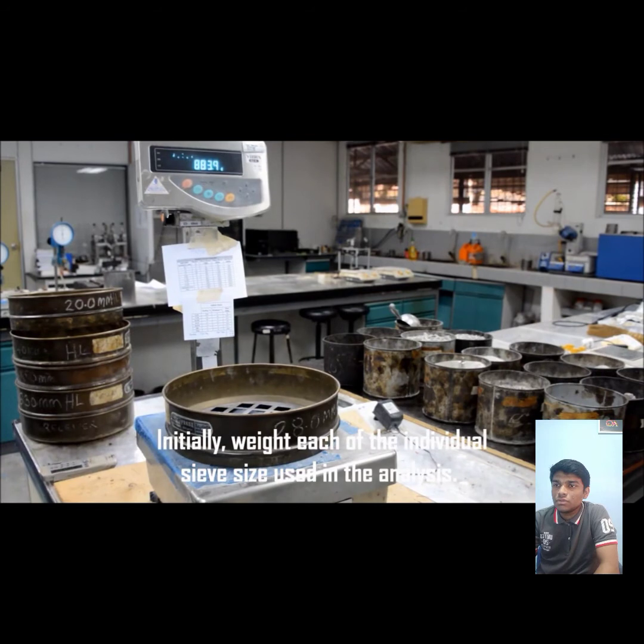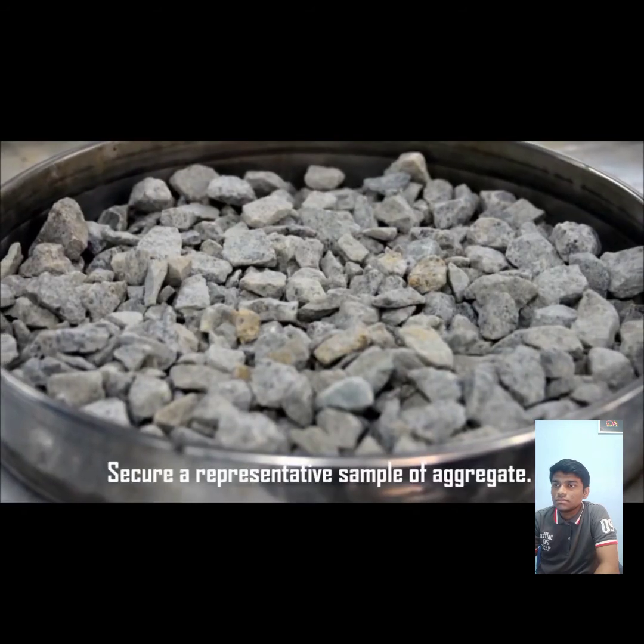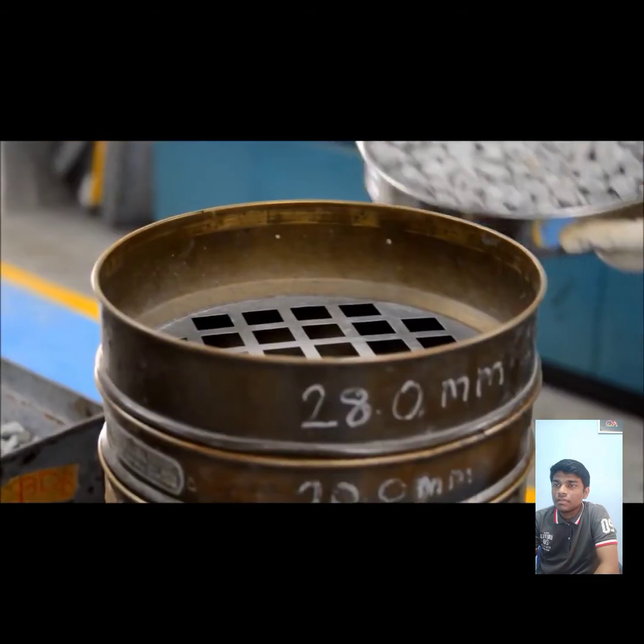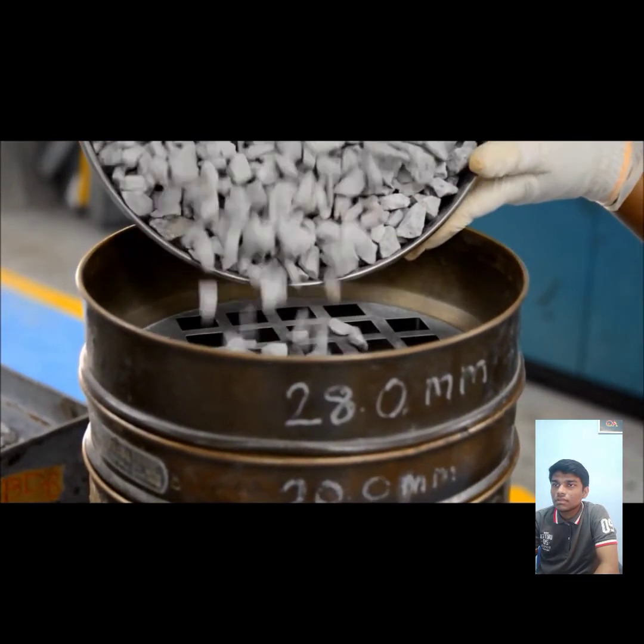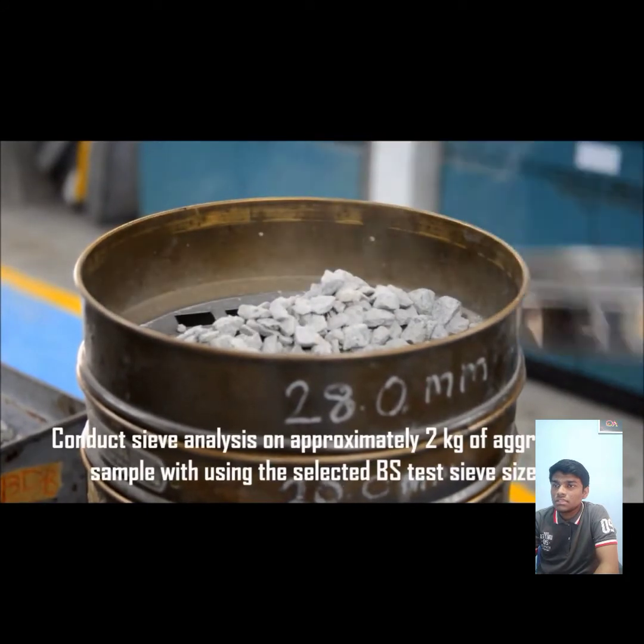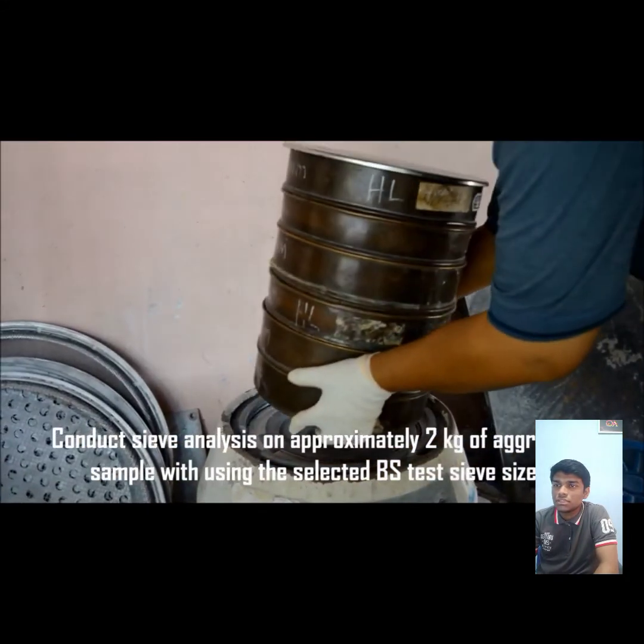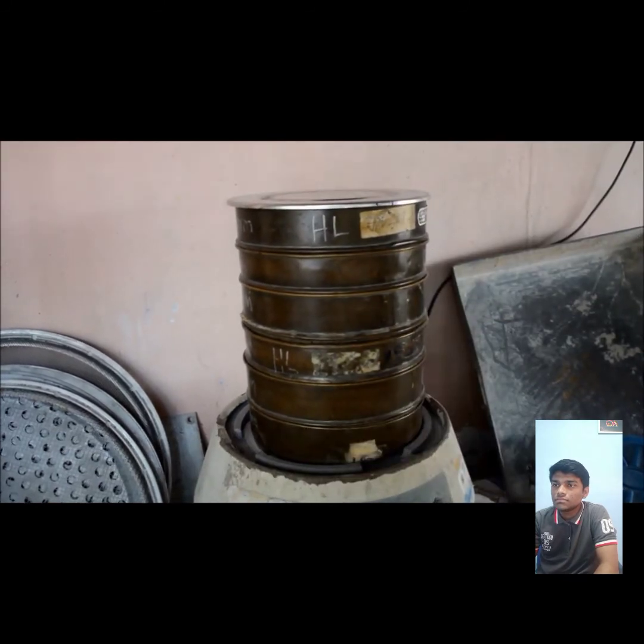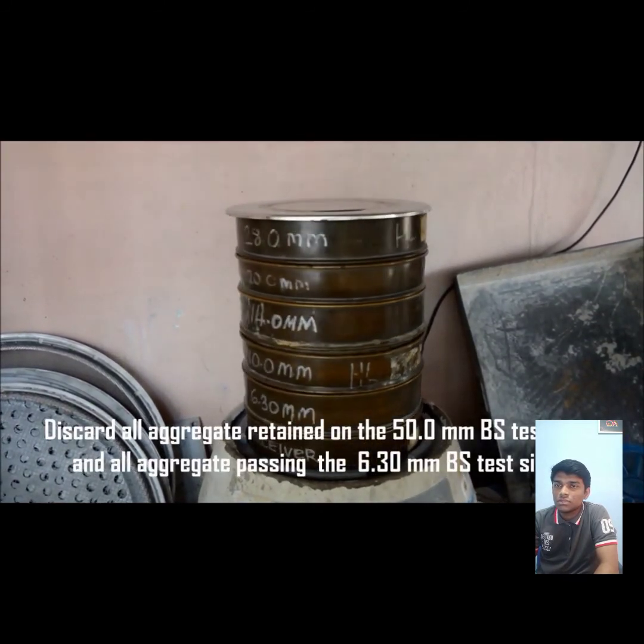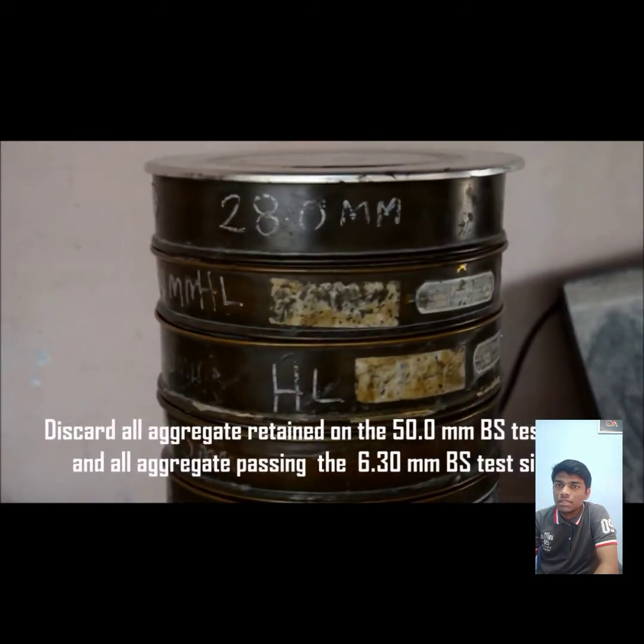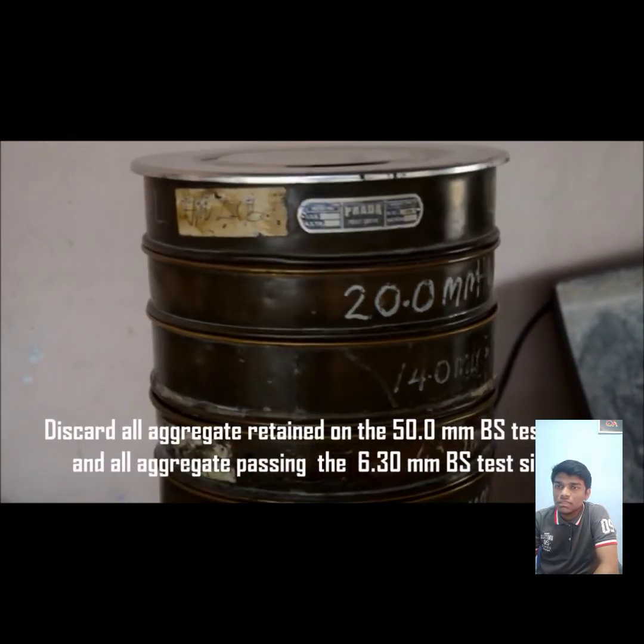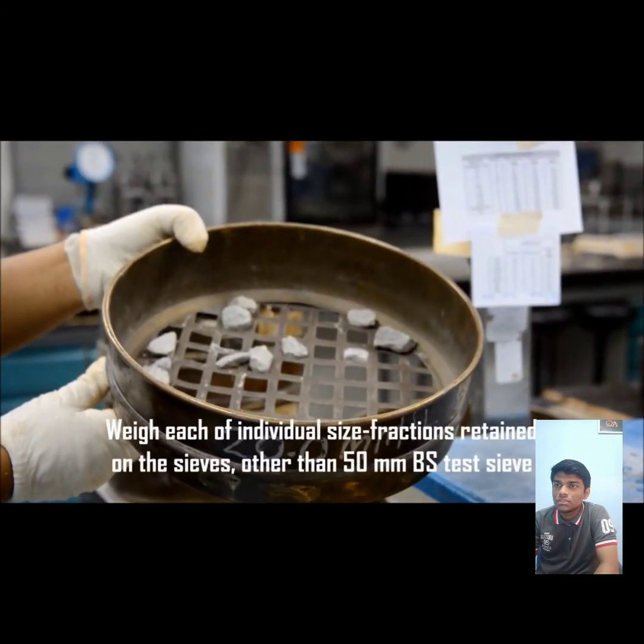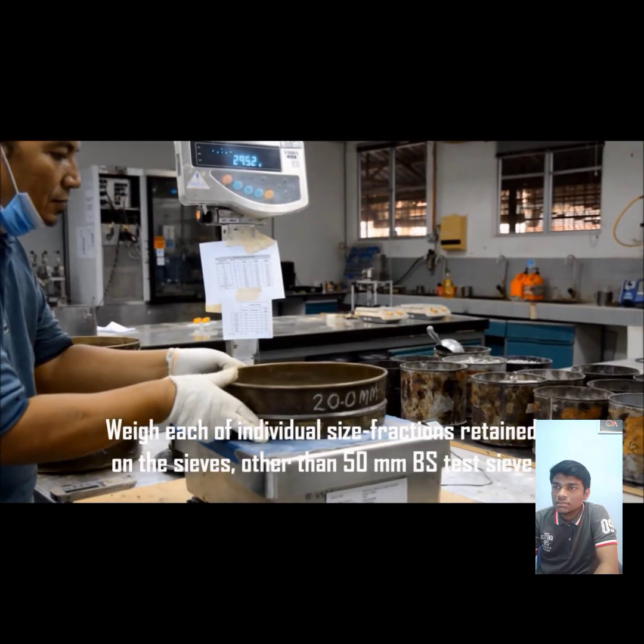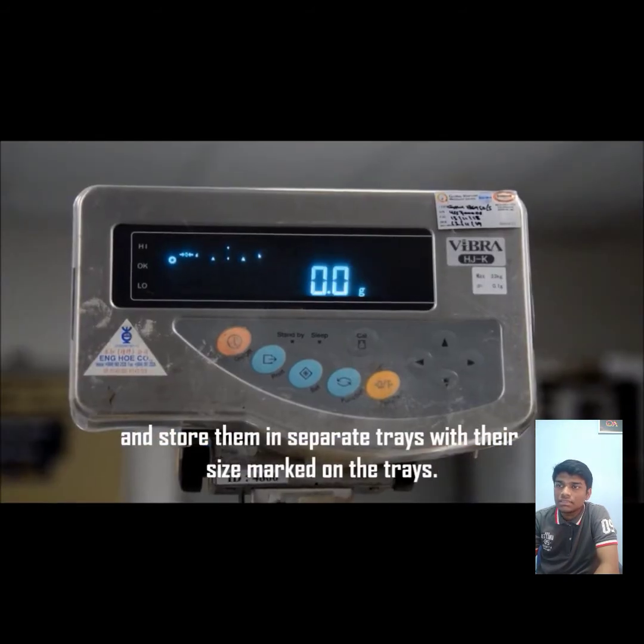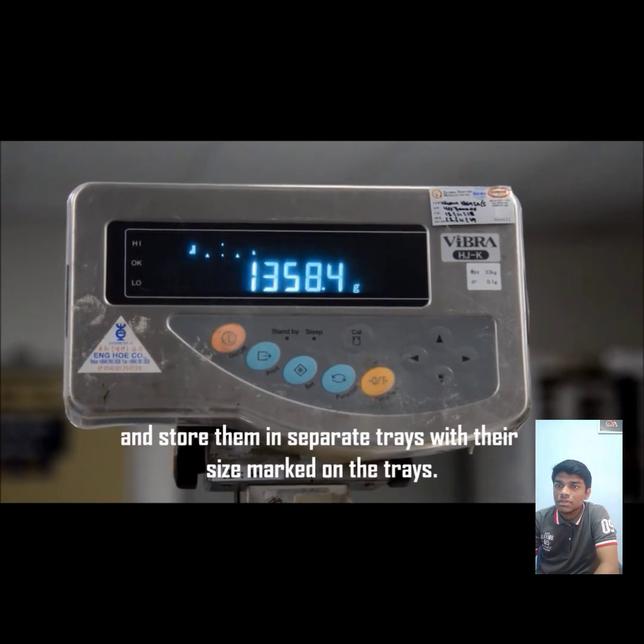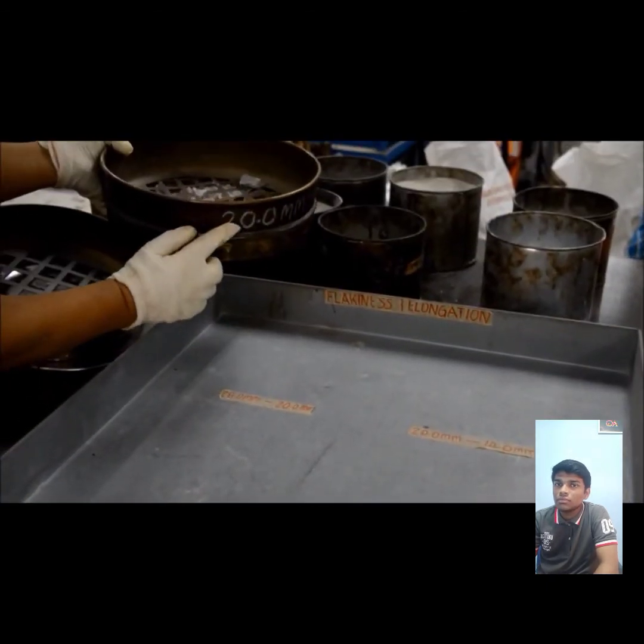We weigh each individual sieve size used in the analysis. Secure a representative sample of aggregate and put it in the sieve. Conduct the analysis of a 2 kg aggregate sample using the selected BS test sieve sizes. Discard all aggregate retained on the 50.0 mm BS and aggregate passing the 6.30 mm BS test sieve. Weigh each individual size retained and store in a separate tray marked with its size.